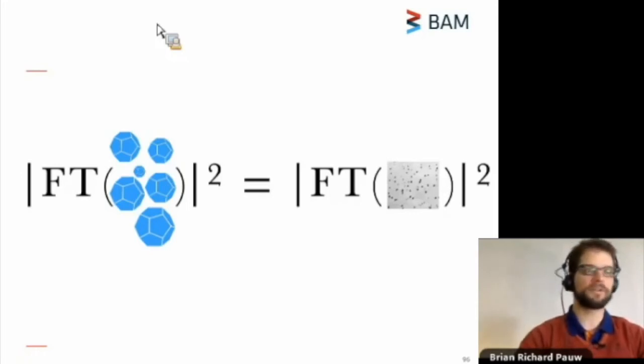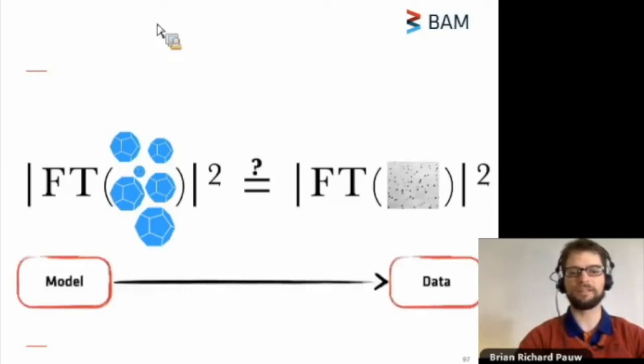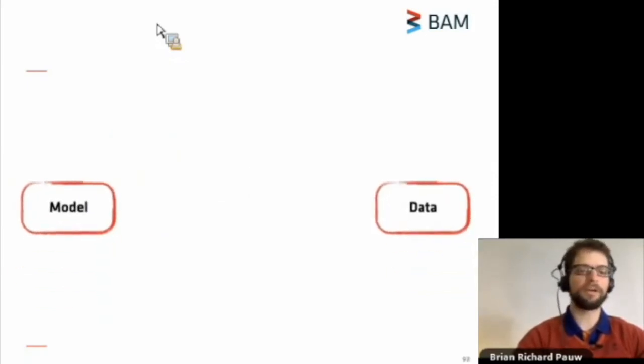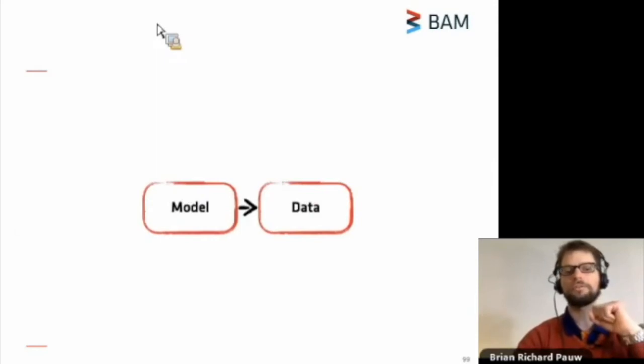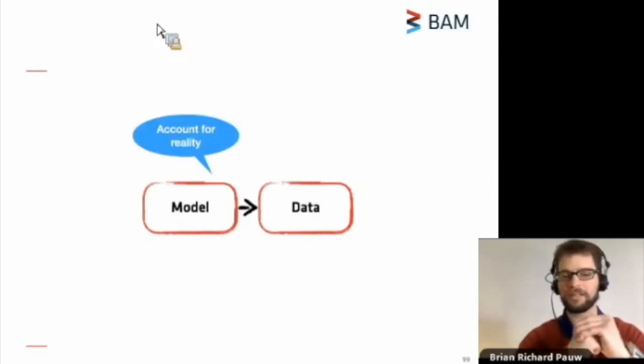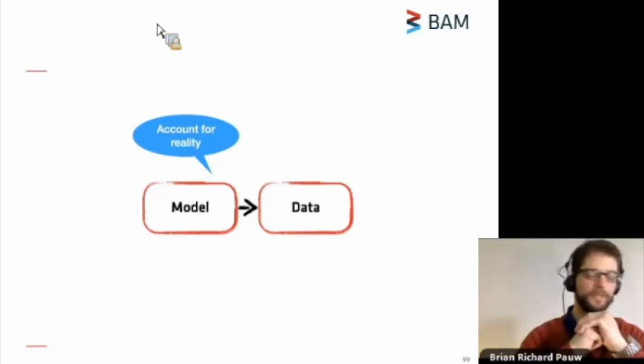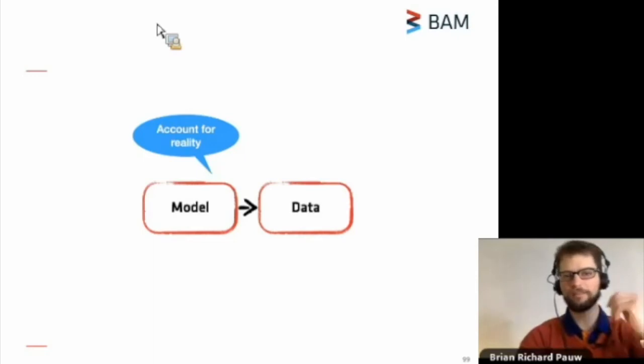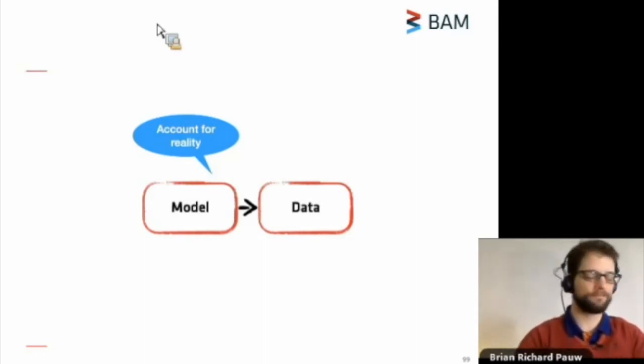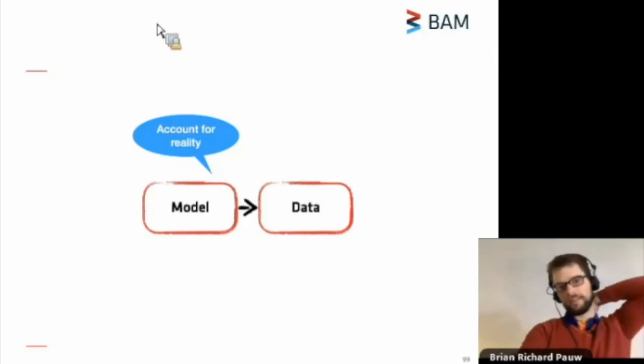Now, this comparison, of course, works the best when you bring the model and data as close together as possible. You can do this by accounting in your model for reality. This means including things like polydispersity in your model, and maybe things like beam smearing. It also means that you have to correct your data. The thing that you collect in your scattering instrument is data, but that is data with a lot of additional signals in it, signals from your sample container, signals as artifacts from the way that we measure. So from all of these signals, you really need to extract just the scattering signal from the analyte that you're interested in. So this needs to be corrected for imperfections.